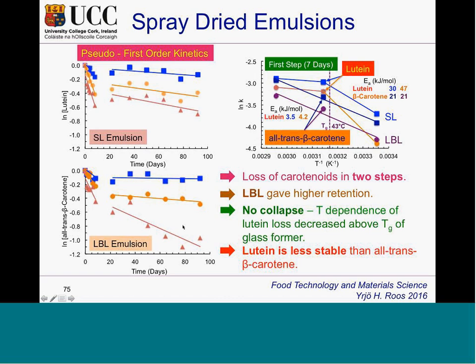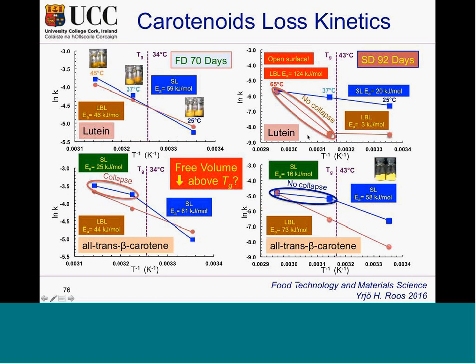We think lutein is somewhat hydrophilic and beta-carotene completely lipophilic. We look at their behavior. We have a little bit different kinetics for those. Lutein sometimes has a higher temperature dependence, especially above the transition, because we believe that it is located on the surface of the particle.